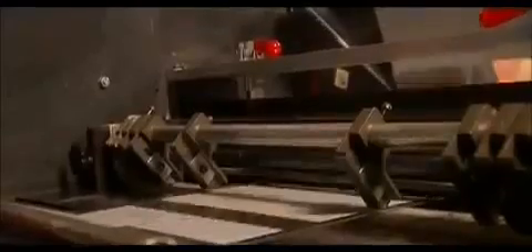The film itself is rubbing against the sides of the ceramic right past the edge. And if you have a material with a low coefficient of friction, the film does not get stretched and you get a better cut. The other thing that makes ceramic good in film slitting is it's a really hard material, so we can put a fine edge on it without getting burrs. Zirconia ceramic is about 6 times harder than steel, but it's also more brittle. We never recommend a ceramic blade in a high impact application because the ceramic edge will chip.